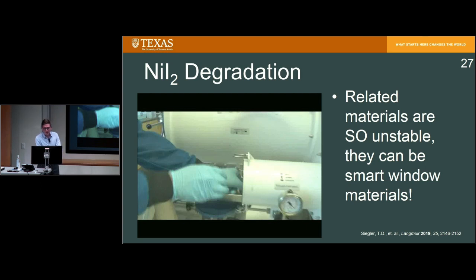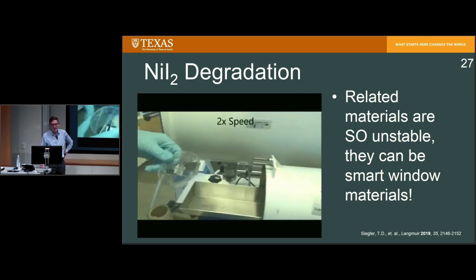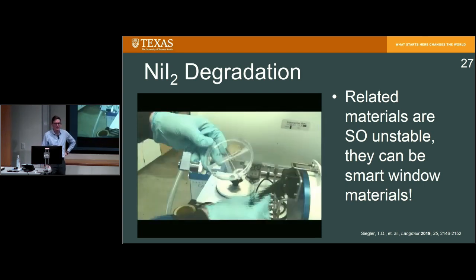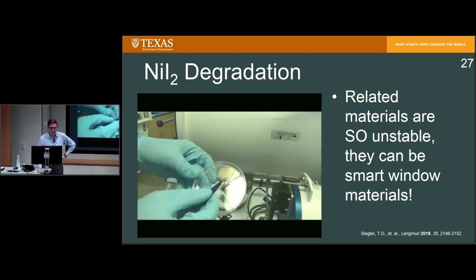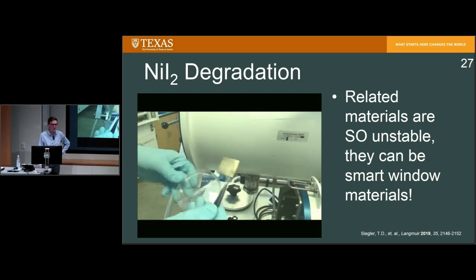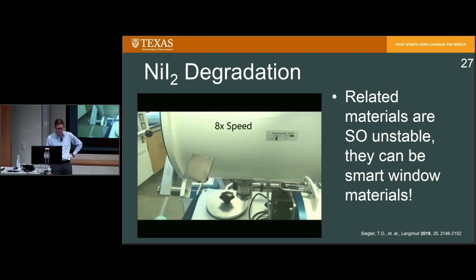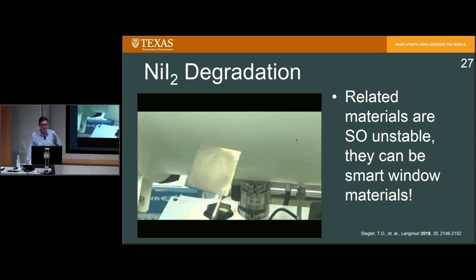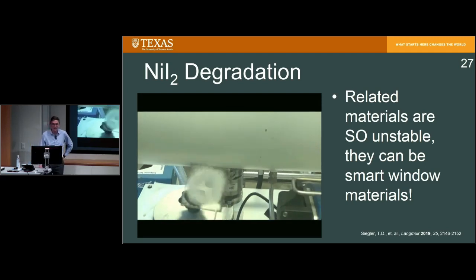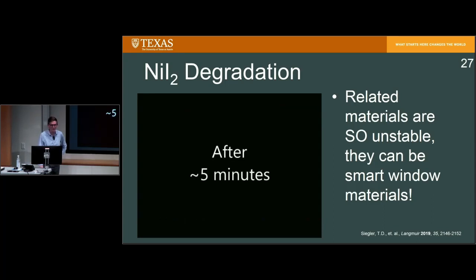In fact, in another paper we were able to show that a related material was so unstable in humidity that the reversible water uptake of the black thin film could be used as a smart window material. Taking a black film of nickel iodide, which is not by itself a perovskite, but it's chemically related, out of the glove box, a controlled nitrogen environment where I synthesized the thin film, you can see that really quickly, within 2 minutes or so, it turns first into a white solid, and then after about 5 minutes, turns into a white liquid that's mostly water, that you can see there.